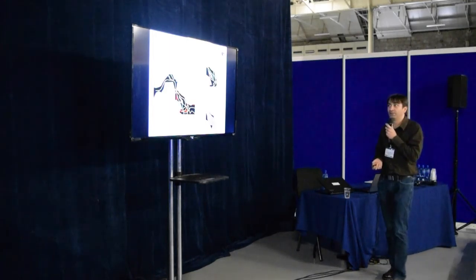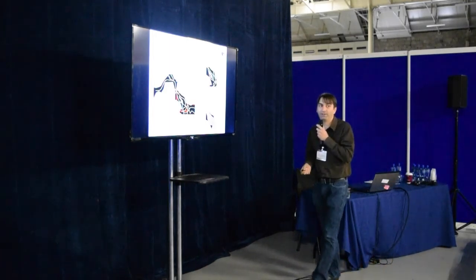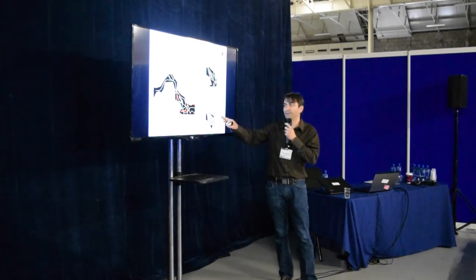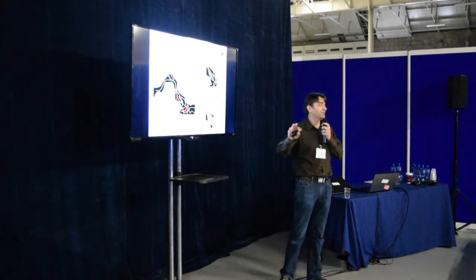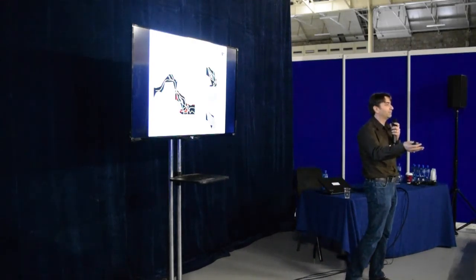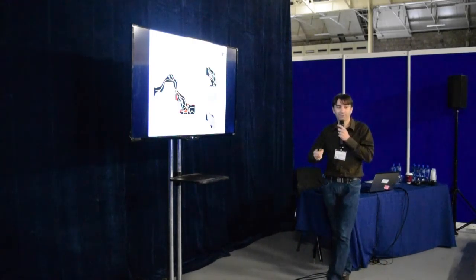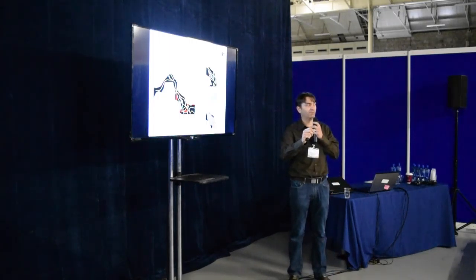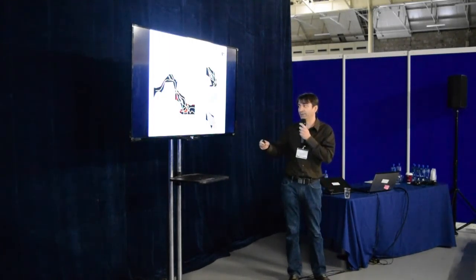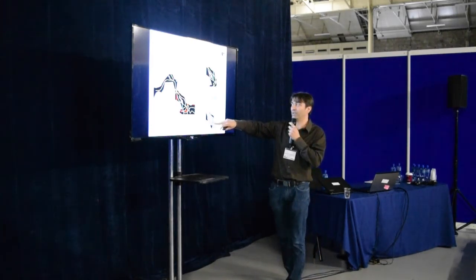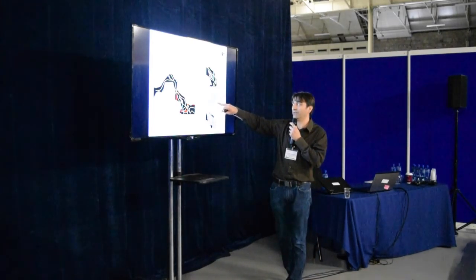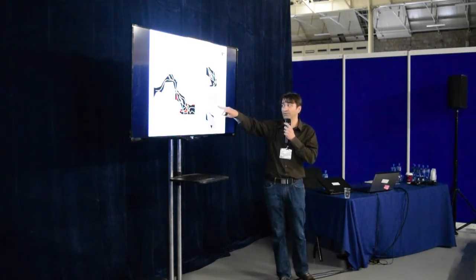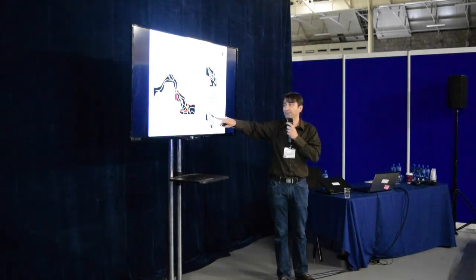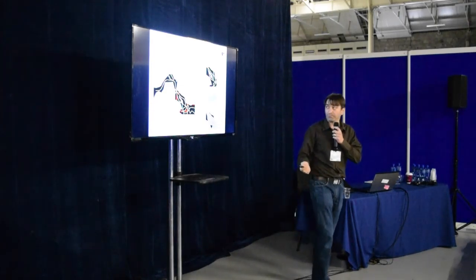Now, the second stage is induction heating. This is a more efficient process. In this process, we insert steel fibers, simple fibers that we can find in any household kitchen. Those steel wool pads that we clean pans with in the kitchen. So we insert that into the asphalt pavement, and then when a crack occurs, we induce induction heating. This heating heats the steel fibers which are embedded in the asphalt pavement, melts the bitumen, and closes the crack and repairs the damage.